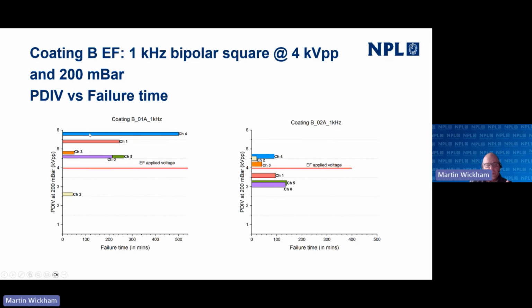So this is plotting, as I said, the time to failure against the inception voltage. So even though we've got no PD at the start of this test, we're still failing these as we go along. Second sample, there's a different distribution of inception voltage, a different distribution of defects within the samples, even though it's the same coating. And you can see here that they're broadly spread either side of the inception voltage, but we're still either side of the electrical fatigue voltage, sorry, but we're still seeing these samples above that voltage, they're still failing.